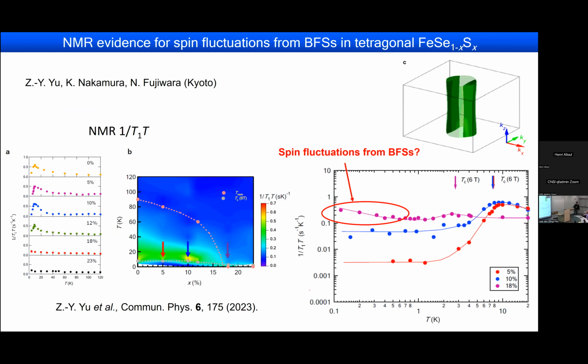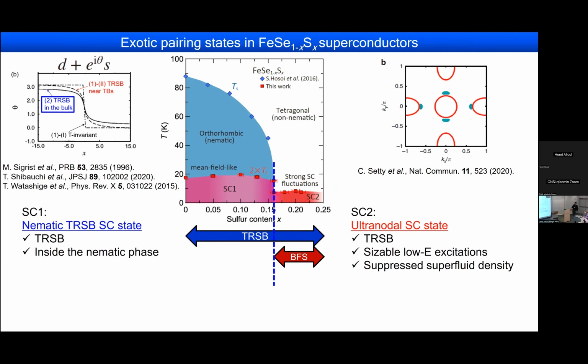Okay, this is the final slide, and I would like to also say that from the NMR measurements, we can also see very strange things happening here. For this 18%, which is in the SC2 region, 1 over T1T in the superconducting state at low temperatures, you see an enhancement of the 1 over T1T, which is an indication that we have some kind of spin fluctuations inside the superconducting state. So that may be due to the kind of nesting properties within the Bogoliubov Fermi surface in the superconducting state.